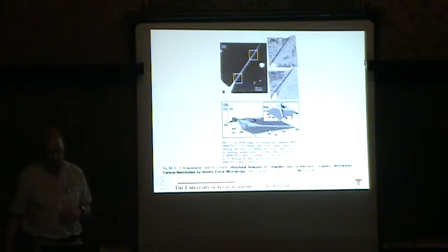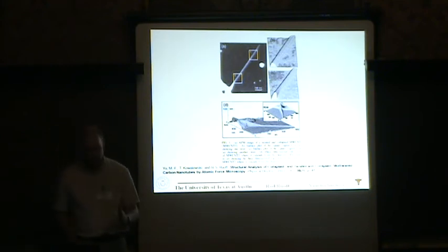And this was kind of interesting because, not surprisingly, if you think of something like maybe an inner tube is not the best example, but as you go toward this conformation, it's going to be very compliant out of plane. The persistence length of a ribbon along the ribbon, such as one of these collapsed nanotubes, is much, much shorter than the persistence length of a nanotube that's not collapsed.